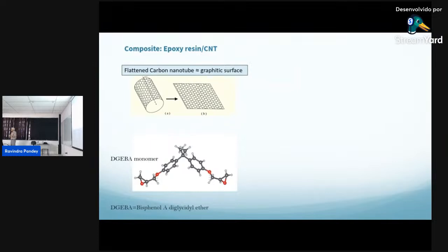So we start again with some approximations. They experimentally use so-called flattened carbon nanotubes. These are very, very large diameter carbon nanotubes, so they have a nice surface. So instead of taking this as our model, we simply go to a graphitic surface, graphene. And then we have, again, I still don't remember all the acronyms, this so-called bisphenol A diglycidyl ether. So I use this acronym DGEBA. This is a simple monomer, not a polymer, a monomer. You can see here it is carbon rings, there are hydrogens, and red are oxygens.